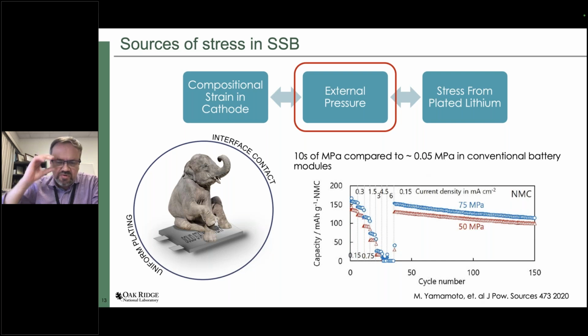Here is one example. Beautiful cycling. You can see minimum capacity fade over many cycles. But look at the stresses applied, pressures applied: 50 megapascals, 75 megapascals. So if you calculate that over the area of your typical car pouch cell, right, that's going to be around 20 tons of weight that needs to be sitting on the battery to make it work. So obviously, for now, most of the prototypes work only in small laboratory cells where the external pressure can be applied. And obviously, that external pressure is another major source of stress inside the battery.